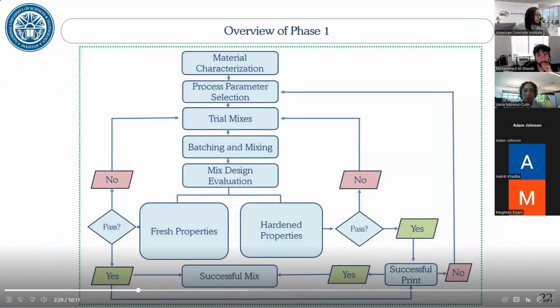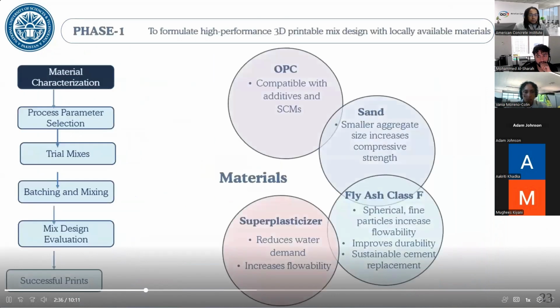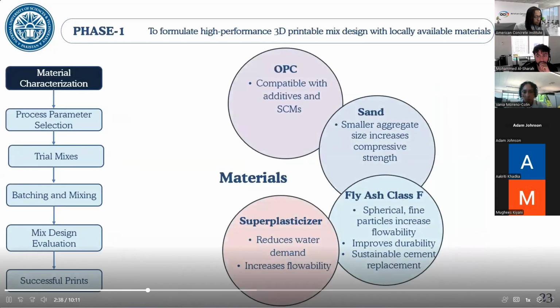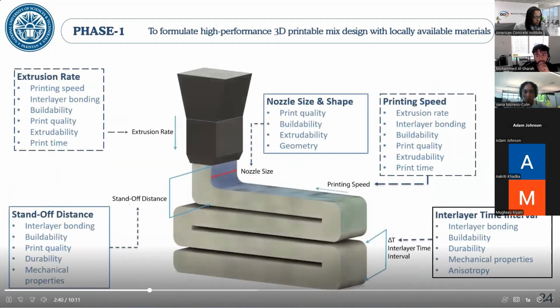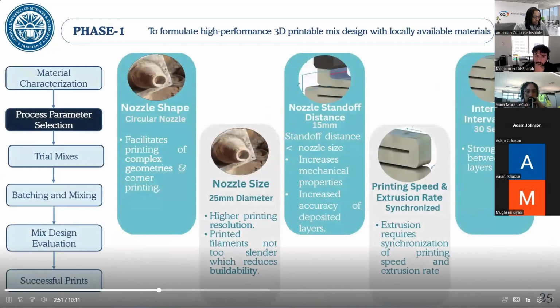After selecting process parameters and adequate mixing, each mix was assessed based on a number of fresh and hard properties. All our materials were locally sourced, and here's the rationale for the selection of each material. Now, this slide gives an overview of the effects of each printing parameter on printing, and that each plays an important role. For print, we chose a circular nozzle as it facilitated the printing of complex geometries.